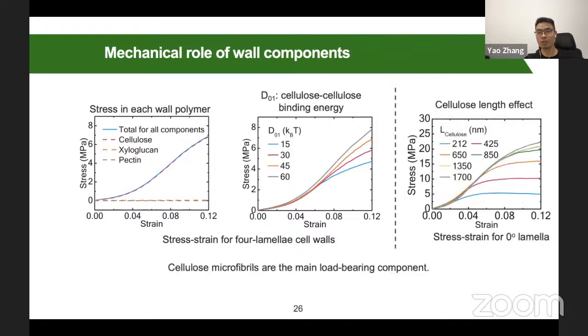And we also try to change the length of cellulose. We found that if you change the length of cellulose, the stress will also change. So it means that it's the cellulose which sustains most of the stress in the cell wall. It also determines the mechanical property of the primary cell wall.